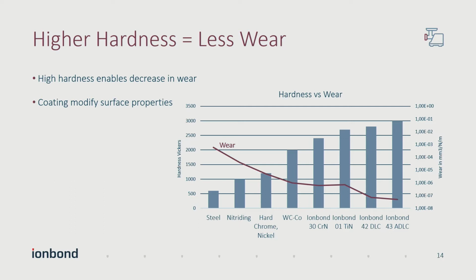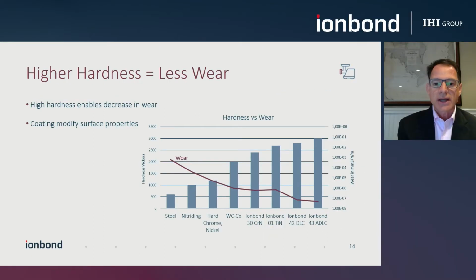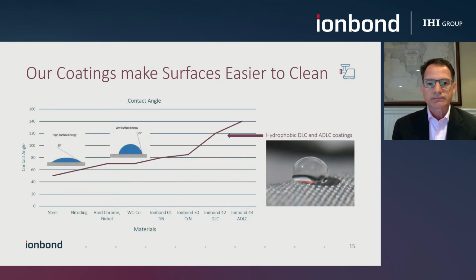So we've really gone from the left over to the right. You'll see, for example, steel. This would be uncoated, maybe nitriding, perhaps a process that you've used, or maybe hard chrome plating, or WCC in this instance. And then next are some of our different coatings, for example the Ionbond 30 chromium nitride, or Ionbond 01 titanium nitride, and then getting all the way down to our Ionbond 43 amorphous DLC. You can see how the hardness properties improve based on applying a coating onto a bare substrate.